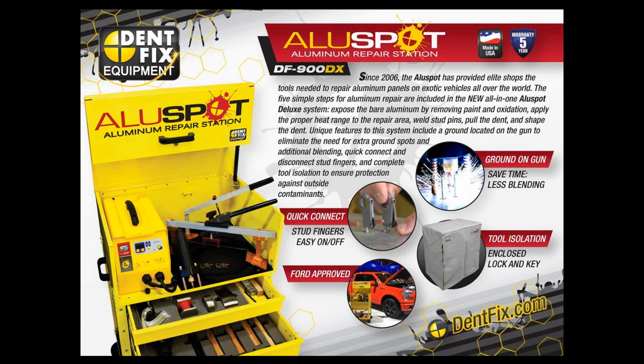And that brings us back to the welder itself, which is a capacitor discharge welder. What happens is the capacitors in here hold on to the energy, and when it releases the energy, it does it through direct current, which fuses the stud on. Literally, right after you pull the gun away, you could put your finger at the weld point, and there would be no heat. And that also applies to the back side of the panel as well. There is no penetration. You're not going through any E-coat either, because the heat is dissipated so quickly.